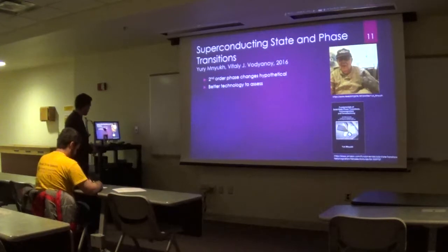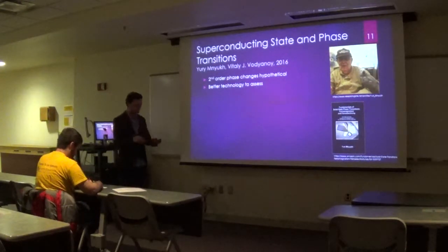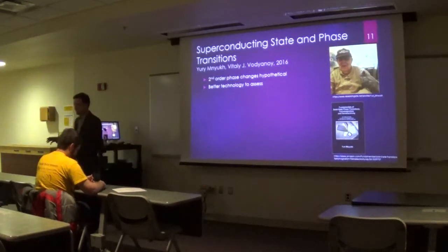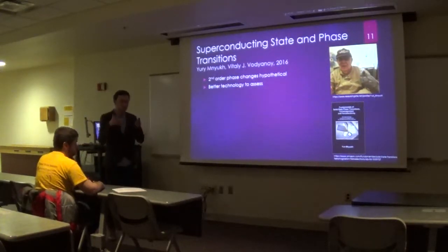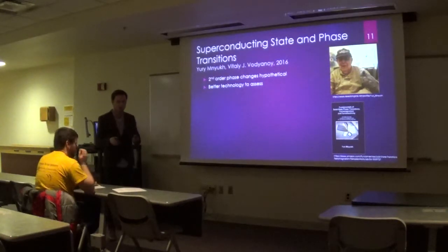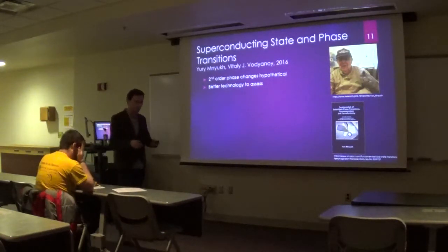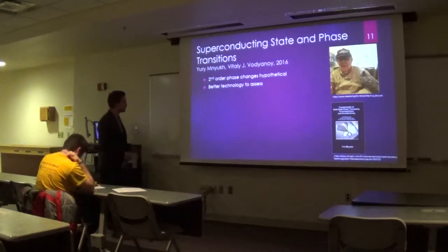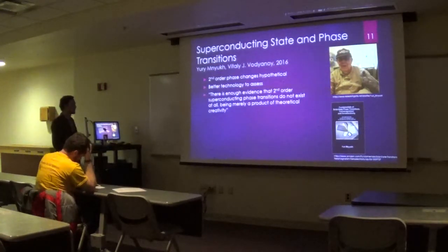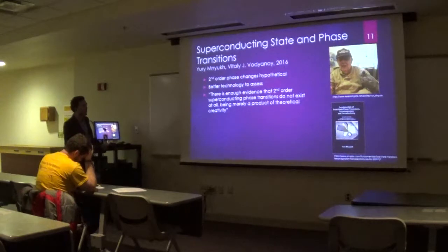So what these two guys did is they took both a theoretical approach and experimental approach, and what they found is that for every single superconducting phase change, we see an abrupt change in our crystal structure of our superconductors before our critical temperature and immediately after our critical temperature. So what they say is that there is enough evidence that second-order superconducting phase transitions do not exist at all, being merely a product of theoretical creativity. This is a big thing, taking down both Lev Landau as well as Paul Ehrenfest.